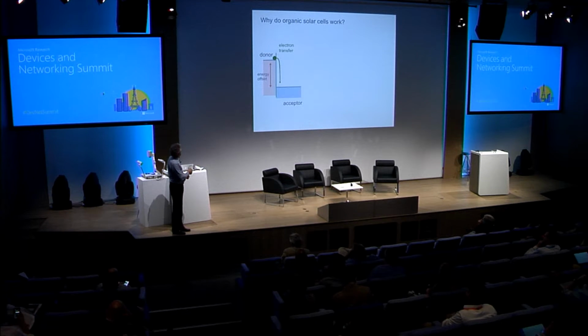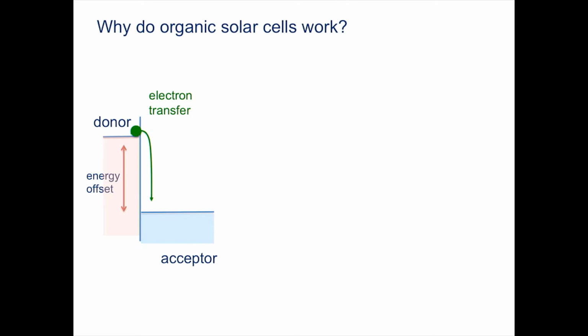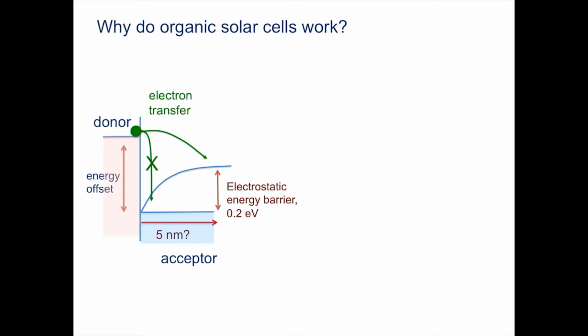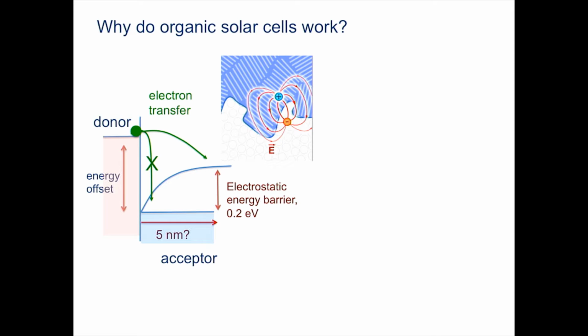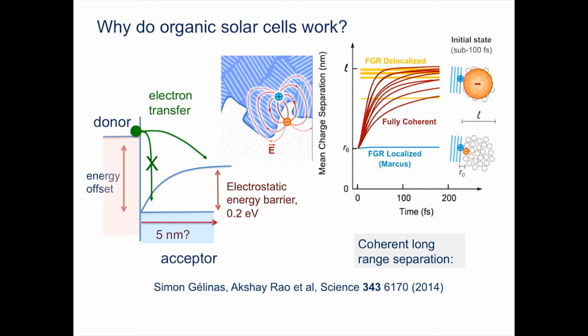So that initial generation step, we push an electron from a high energy state where it's been photoexcited, and it drops down to a lower energy level. And the problem is that the Coulomb potential, the electrostatics, would say, if nothing else happens, the electron appears to get stuck close to where it was generated, and we've got a barrier that has to be circumvented. So it's one of the things we've been looking at in my research group to try to understand how that can work. And we've been looking at the synthetic organic solar cell systems which work really well.